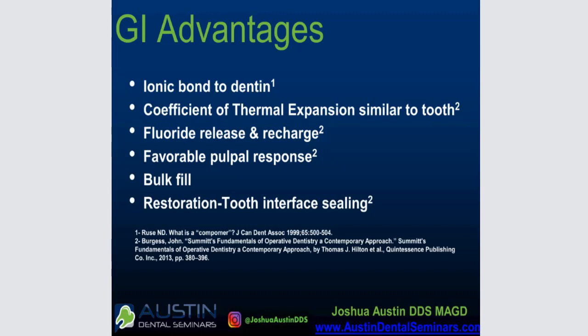Another thing about glass ionomer that is really nice is that the coefficient of thermal expansion is very similar to tooth. And when I say tooth, I'm really referring to dentin more so than enamel. The two are fairly similar. The coefficient of thermal expansion for dentin is around 8, for enamel it's around 11. But when you start looking at composites, the coefficients of thermal expansion start getting over 40, 45, 50. And so those are vastly different, almost 5 times as much coefficient of thermal expansion as you would find with tooth structure. So that can create some issues for us. With glass ionomer, we have a much more similar coefficient of thermal expansion to dentin, and so I think that's another reason why glass ionomer works so well as sort of a dentin replacement.